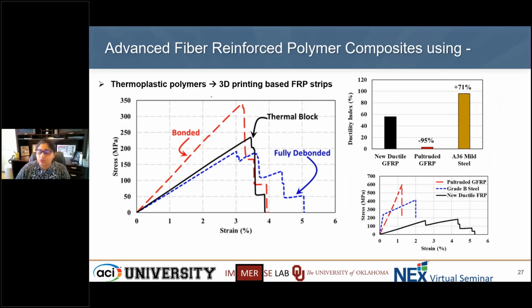So if you look at the stress versus strain in an ASTM D3039 setup, we've seen that these different orientations bonded together in different ways have very unique behavior. If you see a bonded, which is basically saying that all these orientations are stuck together in the layup that I just showed, we have high strength, obviously, because the shear transfer is very effective. The bond is very strong between these different orientations. But you see more of a progressive failure, which is step-by-step failure. And that is happening purely due to the modulus of elasticity of those orientations and how much of an area of the composite that orientation is occupying.